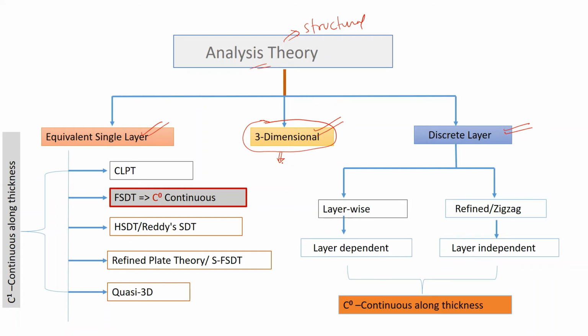So we are very much constrained in using the three-dimensional theory, because when we have to use the finite element approach, it becomes very difficult. For different boundary conditions, it gives very good, accurate, exact results only for very simple boundary conditions and simple stacking sequences of the laminate. So we have the drawback that we cannot use it for the general case, for any stacking sequence or any angle of rotation of the lamina. So we can't find that, and we have to go for other options.